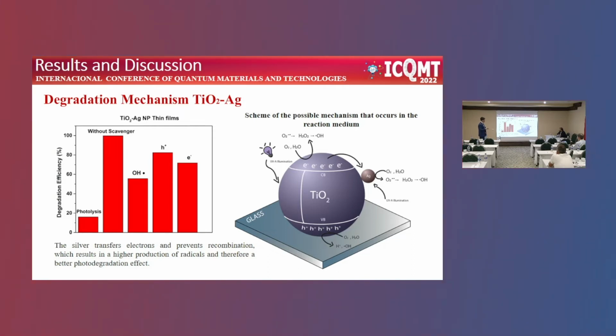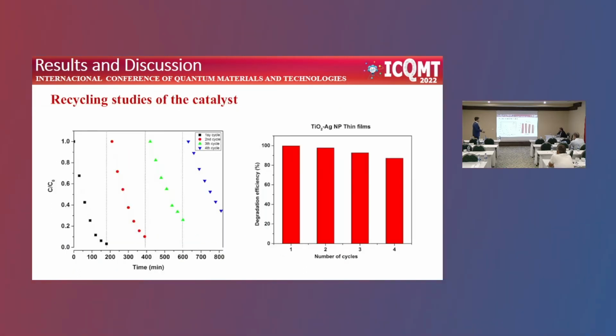So the titanium oxide generates this electron-hole pair separation, and the electron can jump to the conduction band, but the silver nanoparticles can accept these electrons in order to produce more reactive species in comparison with only the titanium oxide alone. So this is the possible mechanism by which the photocatalysis is really better in comparison with only the titanium oxide alone. Well, the recycling study of the catalyst is mandatory in all catalysis studies.